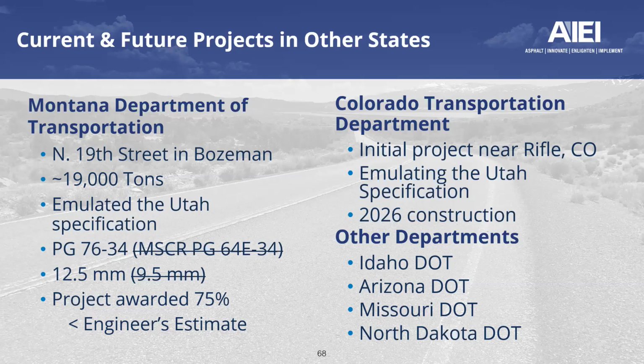The project was originally going to be utilizing a MSCR grade and a 9.5 millimeter gradation. This was before Utah had come up with a 9.5 gradation of their own and specification. The bottom line is that the mix design with those two materials struggled. A lot I could talk about that I don't have time for in regard to that. The short version is that they did have struggles, and so approximately 2 weeks before the project was to begin paving, a change order was initiated where they dropped the Utah spec in, utilizing the 76-34 and 12.5 millimeter.